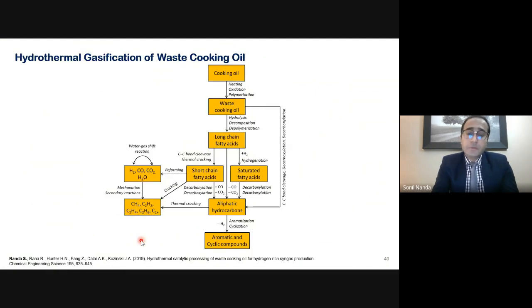So we also performed a hydrothermal gasification of waste cooking oil, and the results almost gave a similar trend. At high temperature, we got high hydrogen yields. At longer reaction time, we got high hydrogen yields, and at lower feed concentration, the yields of hydrogen and methane also increased. So here is a flow chart of the different process flows of different components that we determined from the hydrothermal gasification of the waste cooking oil.